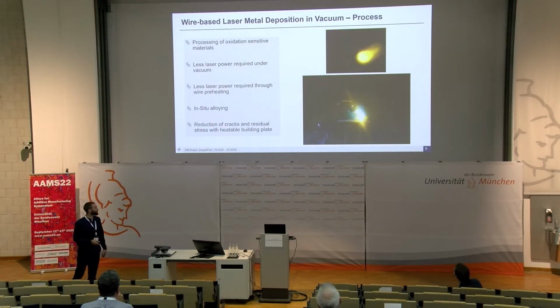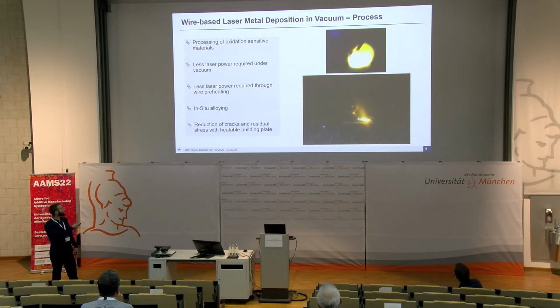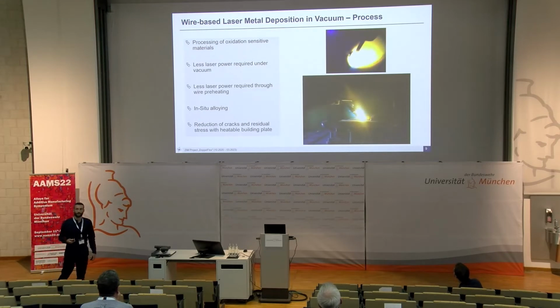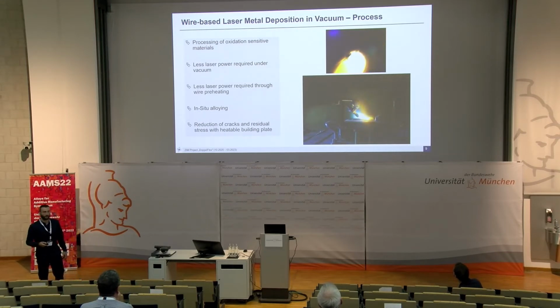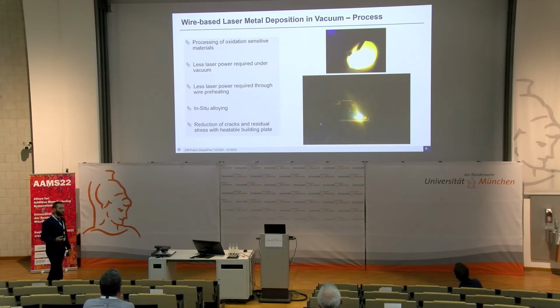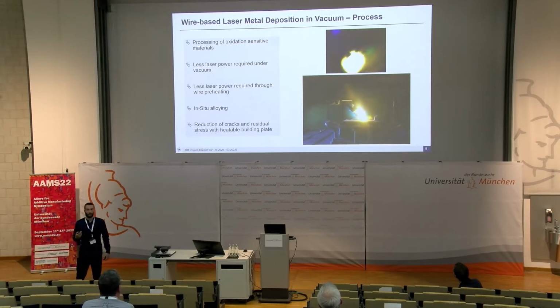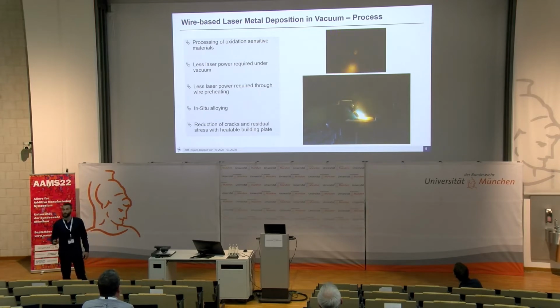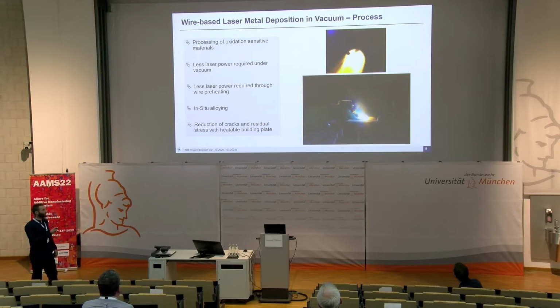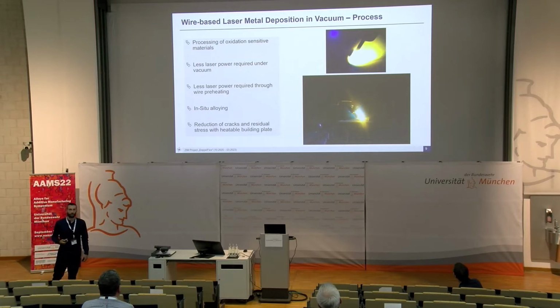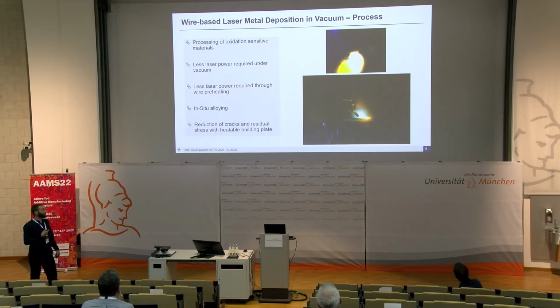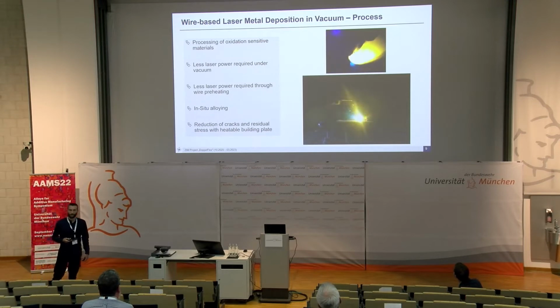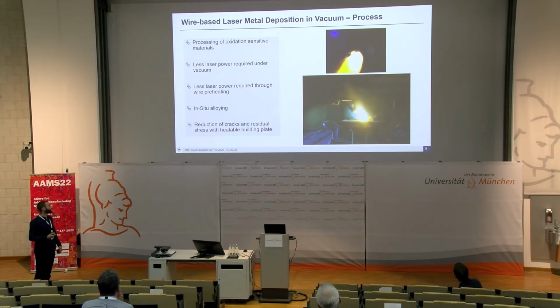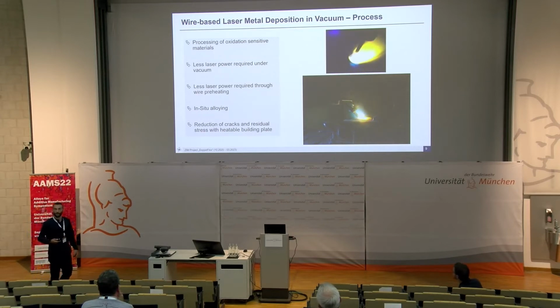So let's have a closer look at the process. You see it one time from above and one time from the side. We have a few advantages. We can produce oxide-sensitive materials without having any oxides in the material. Also, through the vacuum, we can reduce the laser power needed, and we can also reduce the laser power through our inductive wire preheating. What's also possible with the two wires is the in situ alloying of new materials. And we hope, maybe we know a bit more at the end of the presentation, that we can have a reduction of cracks and residual stresses through the heated building plate.